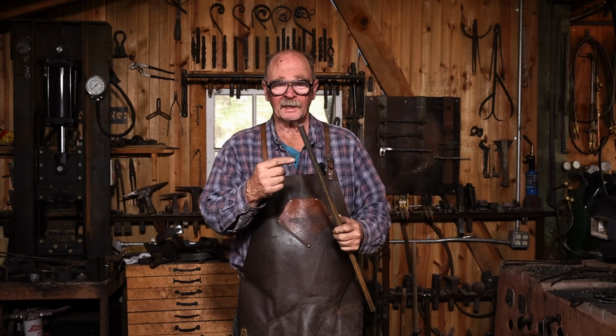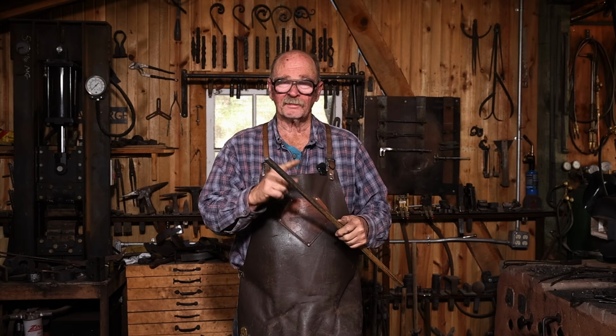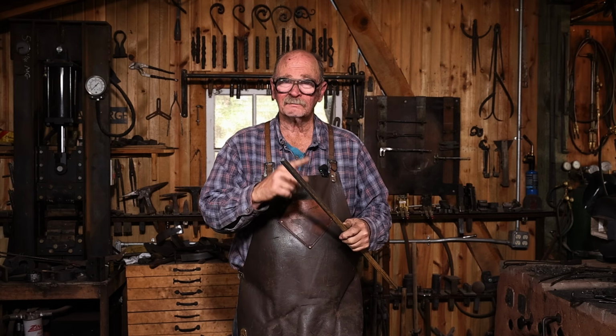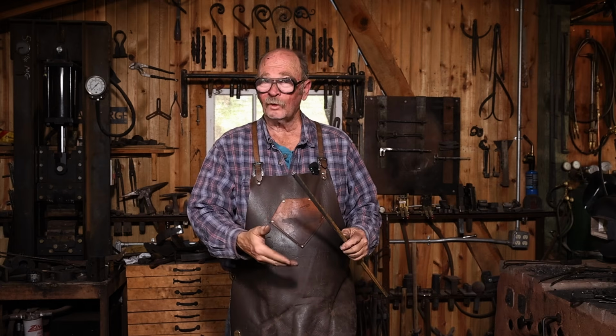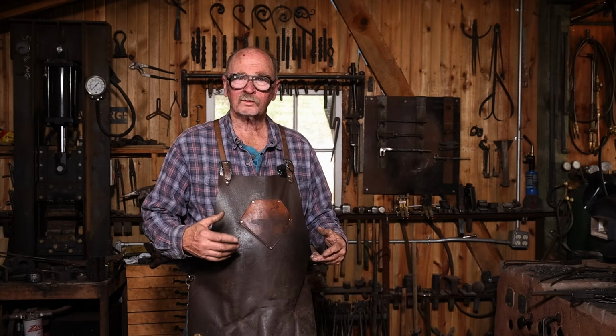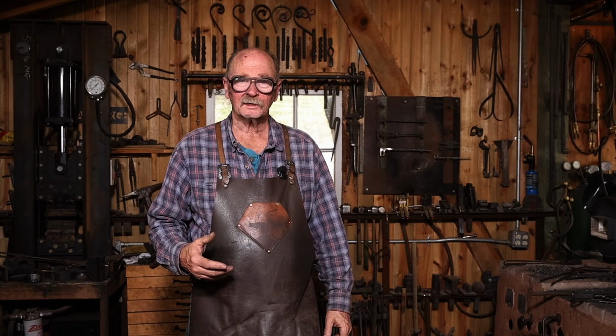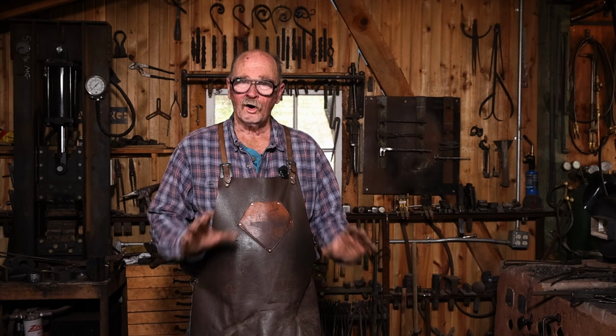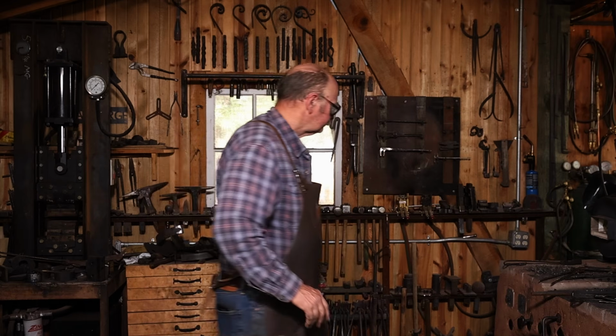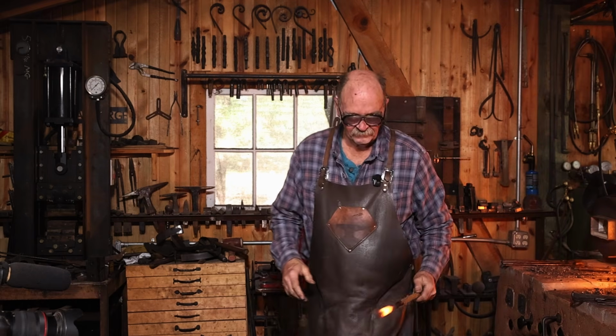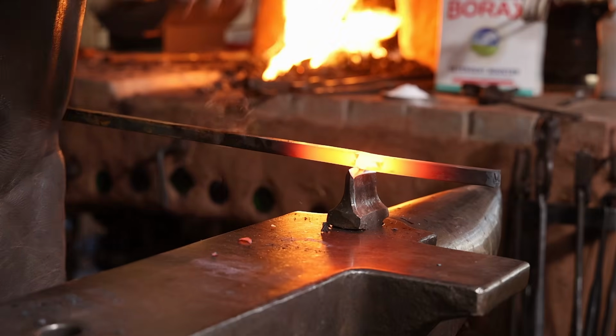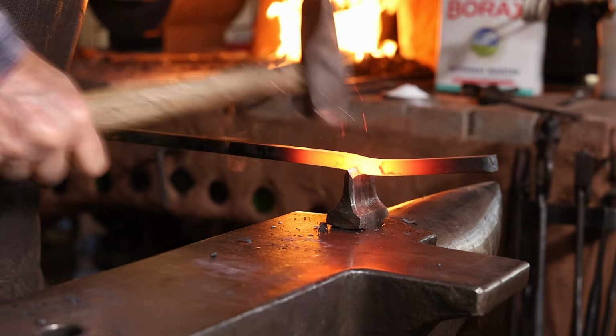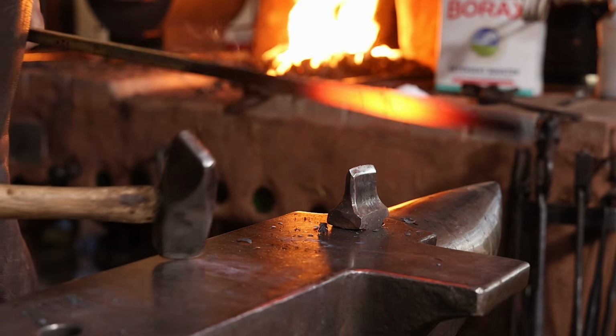I'm going to start with a piece of 1/2-inch bar. I'm going to nick it about 3 or 4 inches back on a Hardy, about halfway through, and then fold it back over on itself. This way we don't have to be manipulating material as we come to the anvil. All we have to do is make the weld. Got about halfway through.